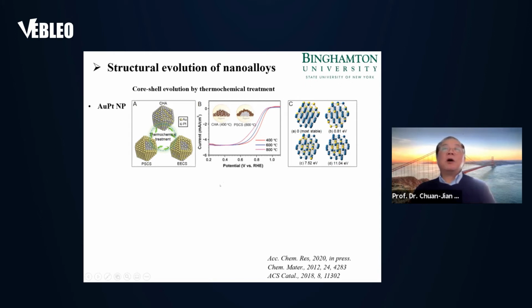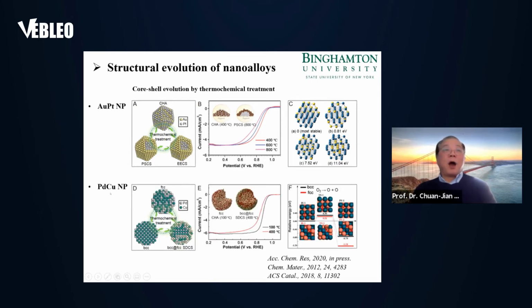So you can use a thermochemical treatment. In the bottom, using palladium copper nanoparticles. In this case, although we don't have much surface enrichment, we see a phase structure change. The surface is enriched with the FCC structure at a higher temperature treatment, in comparison with the core structure, BCC structure. And if you do computation, DFT modeling, you can show the activity for the FCC structure is higher because it has lower kinetic barrier.